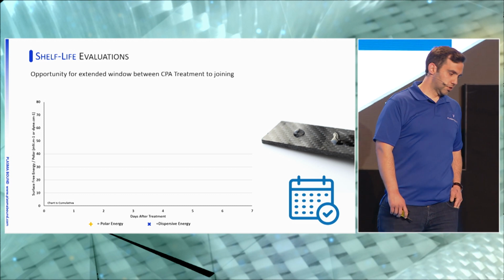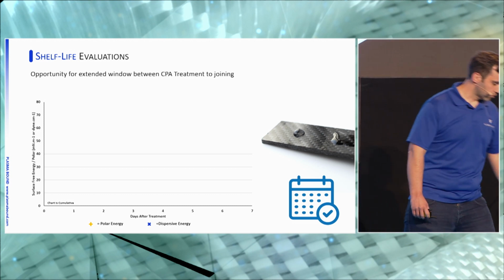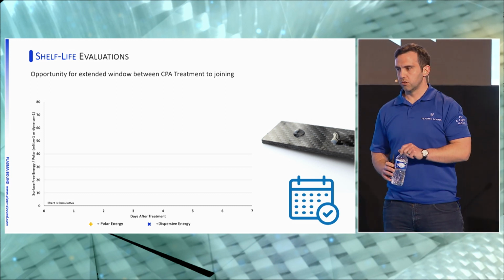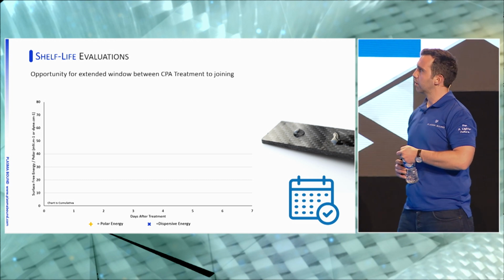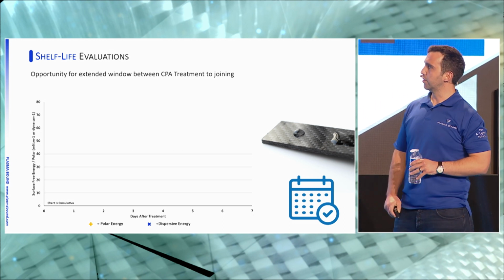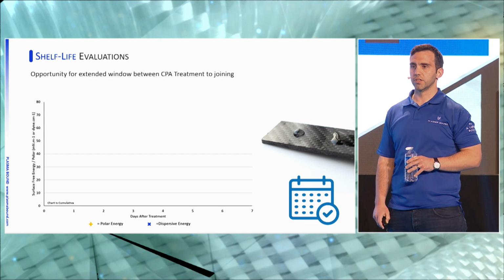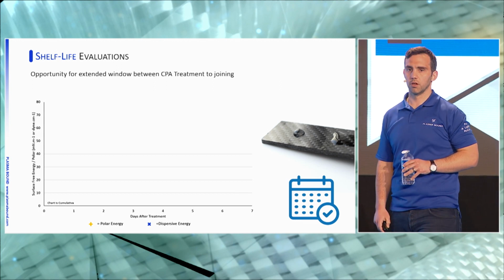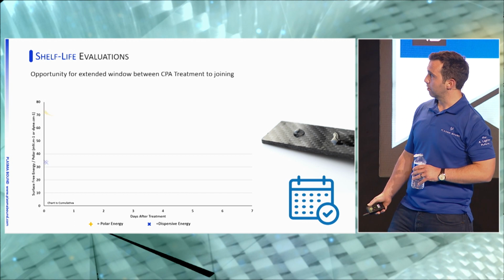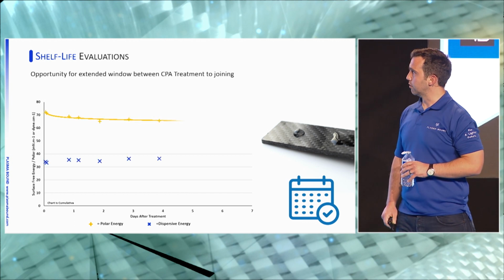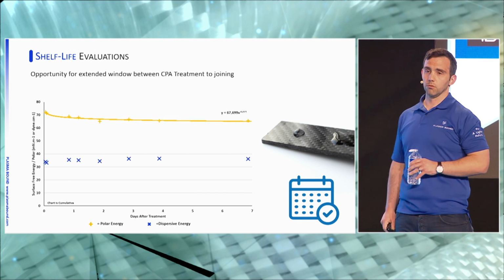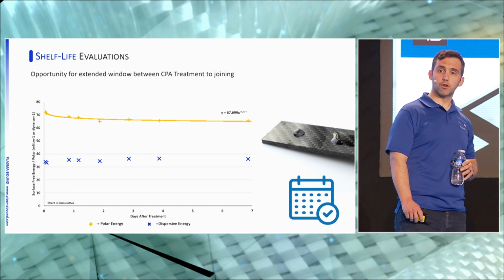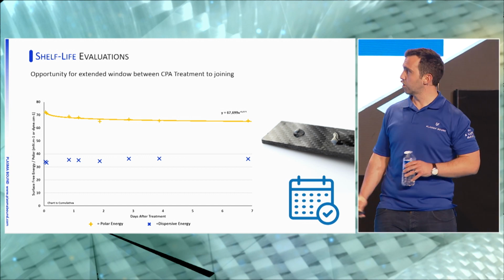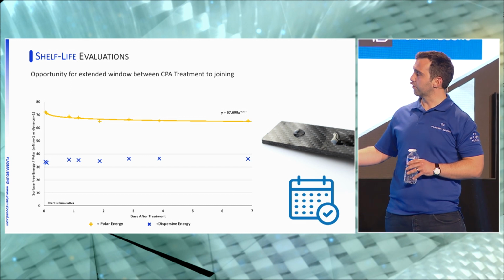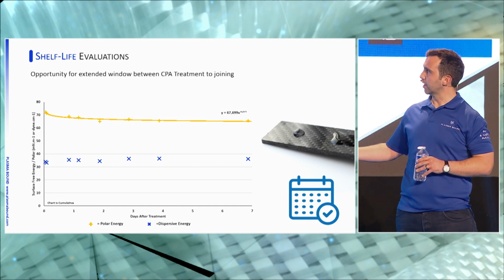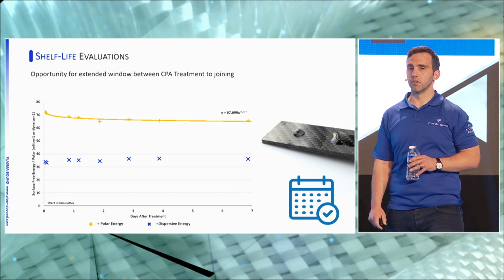And what's more, that customer was more interested in, right, so you can give that benefit to us, but what will you end up causing us in the long run? So if we started this process, do we have to bond within 5 minutes? Do we have to bond within 2 hours? How long? The answer, when we carried out evaluations, was that 7 days later, we were still at a very similar number to what they required. Essentially, we started out at 72 or 73 dyne. We finished up at 68 dyne. It was still above the requirement that they had.